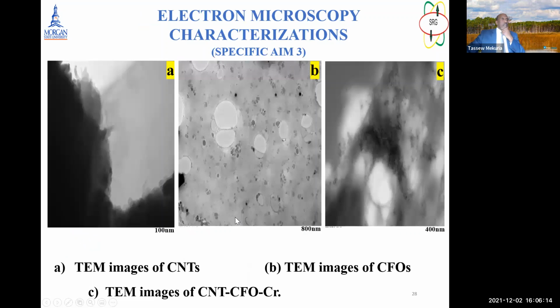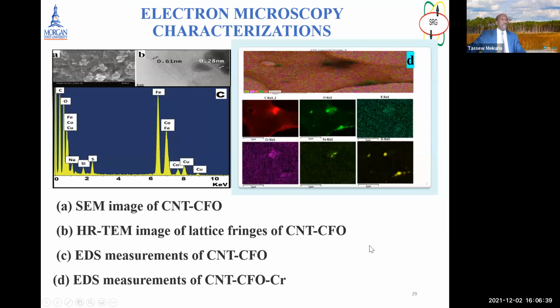Okay. And we tried to observe the TEM image of CNT here. As you can see, B is the TEM image of CFOs, and C is the TEM image of CNT CFOs with chromium. This one is just to see what this looks like, with scales of 100 nanometer, 800 nanometer, and 400 nanometer.